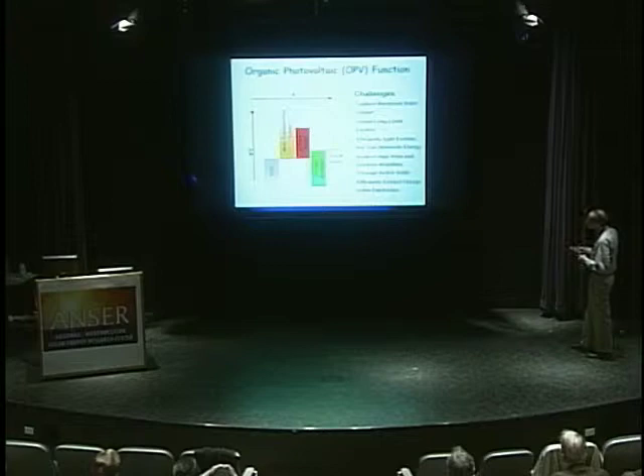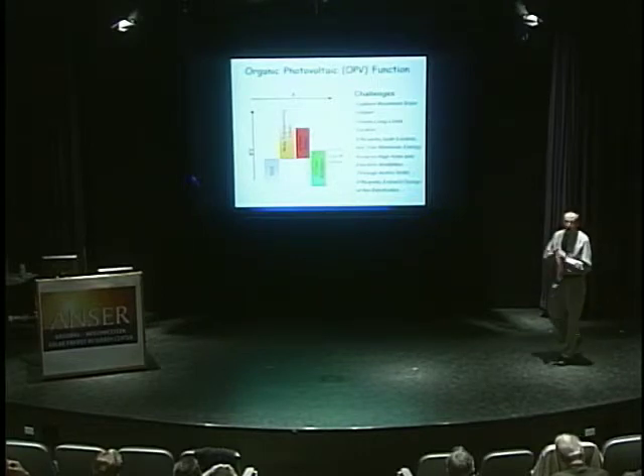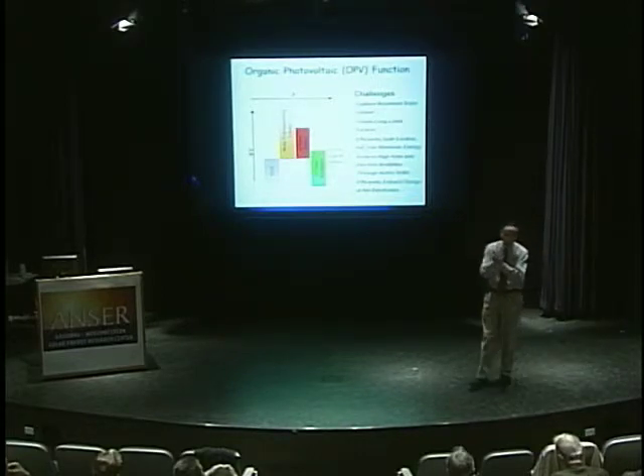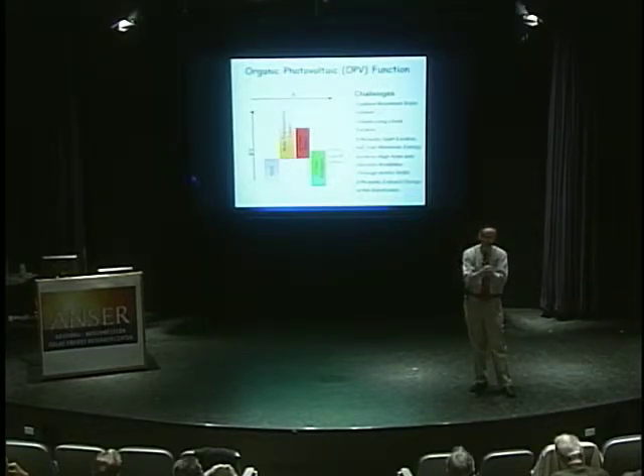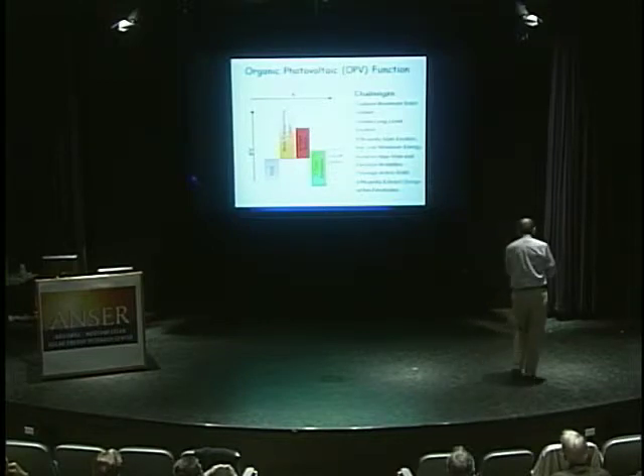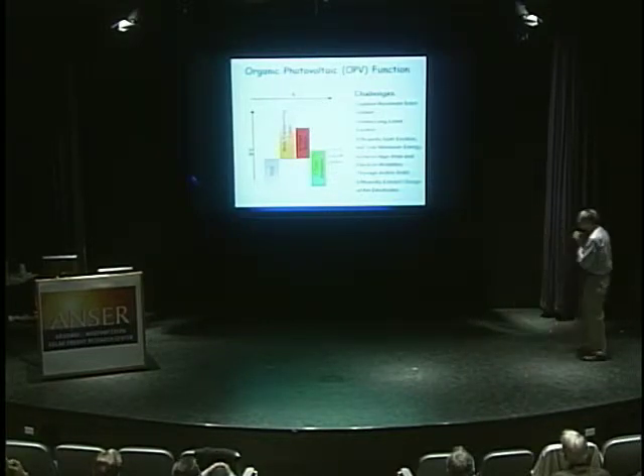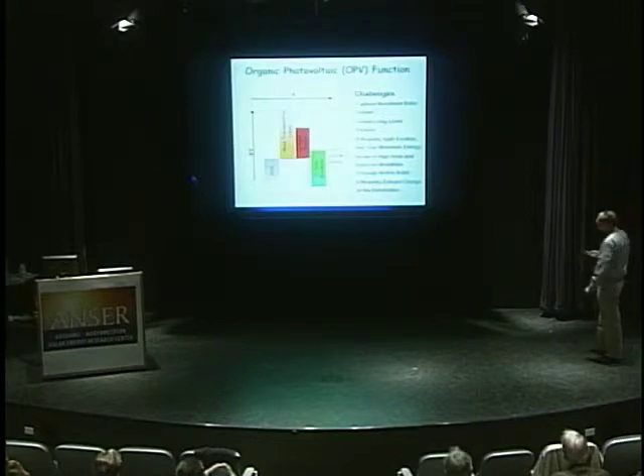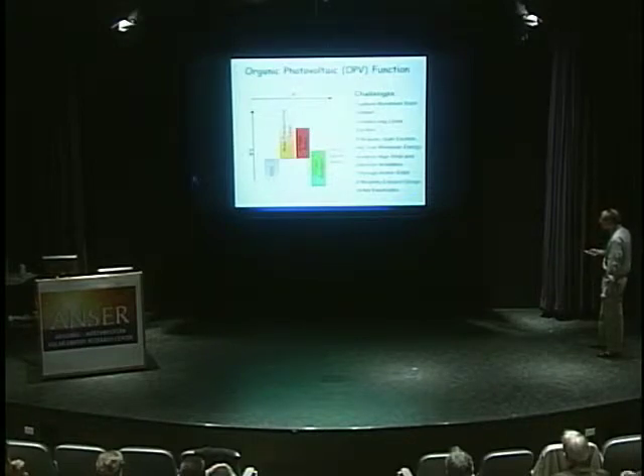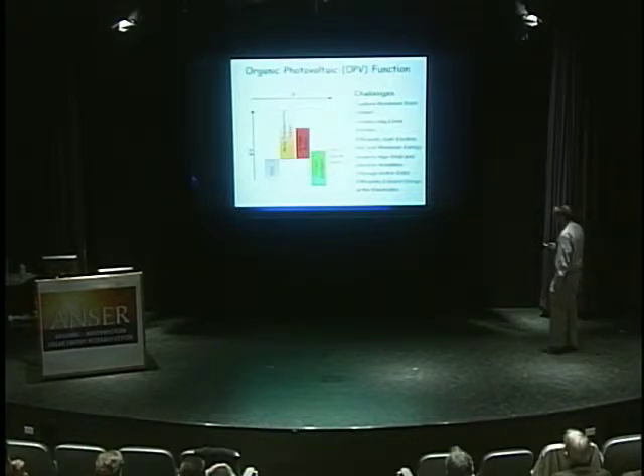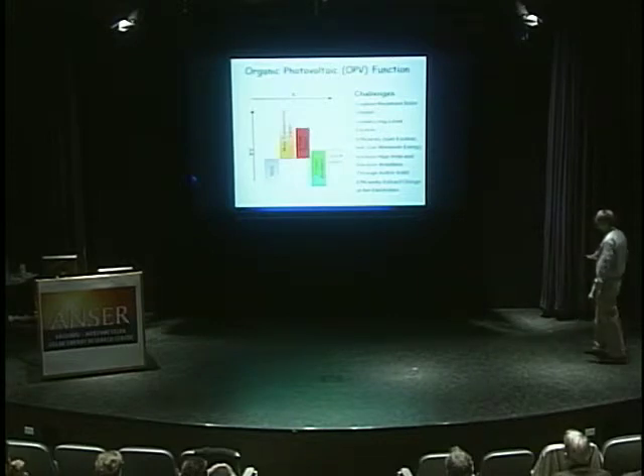There has to be some sort of layer against this electrode that compatibilizes the rest of the active structure with the electrode for a whole bunch of reasons. Everything from planarizing to adjusting work functions to smoothing the differences in surface energy. There'll be a p-type donor material and an acceptor, and then a low work function metal cathode. So this is the anode, and this is the cathode.